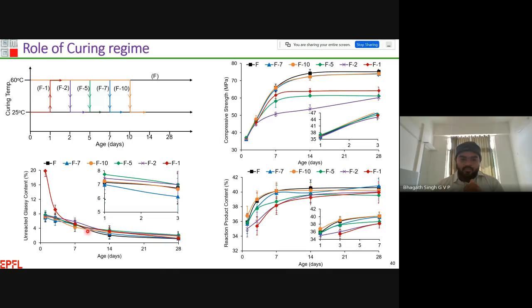I observed a similar trend in the unreacted glassy content as well as the reaction product content. Whenever I increased or decreased the temperature, I could see a drop in the reaction product as well as a drop in the unreacted glassy content. We also tried to identify which type of product is formed in the system, and at all the locations I can see only silica, alumina, and sodium incorporated in the reaction product. Even though we changed the temperature from 60 to 25 or 25 to 60, the product content is the same. This is another interesting finding from our research. How does the product type influence the ultimate strength? As I said so far, the silicates are important and also the reactive alumina content. How does the silica to alumina atomic ratio in the structure ultimately influence the ultimate strength?